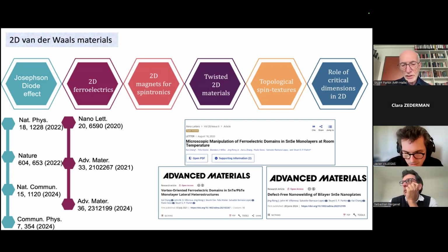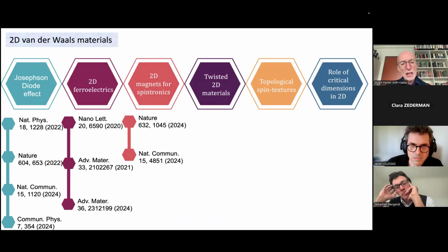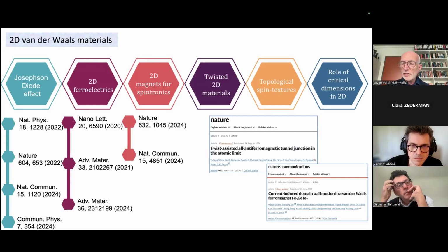This leads to a very interesting ferroelectric valleytronic tunneling junction device, which again, I don't really have time to discuss. We've also shown the possibility of nano-welding of islands of these ferroelectrics through high lubricity of these layers. One thing that we feel is extremely interesting for racetrack is that we've been able to demonstrate the current-induced motion of domain walls in a 2D ferromagnet.